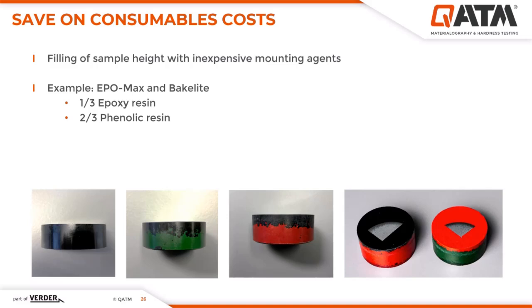It is also possible to combine different mounting materials to reduce the cost of consumables. If a sample requires the use of a high-quality epoxy resin, this can easily be combined with a more affordable phenolic resin as a filler material. In my example, I first used 3 scoops of epoxy resin. So the picture on the left side, the black sample. In the second step, I used only 1 scoop of epoxy resin and then filled the rest of the press chamber with 2 scoops of bakelite. One example with green or with red bakelite. Since epoxy resin is about 3 times more expensive than bakelite, this approach saved around 40% of the material costs.